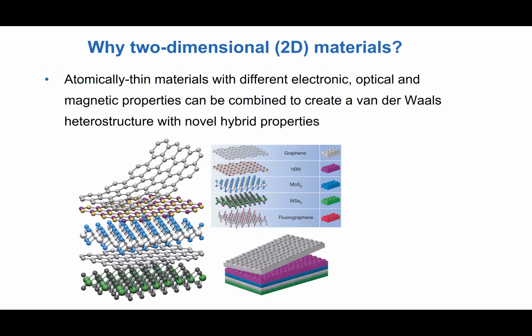In my group, we work primarily with 2D materials, and I think you might have heard about these materials. There are outstanding scientists at Harvard, MIT, and all around the world working with these. The idea is that there is a very large family of materials, more than 5,000 by the last number I know, which have very strong bonds between atoms in the plane and weak van der Waals bonds that connect different layers. These layered or two-dimensional materials have the fantastic property that one can use rather mundane ways like Scotch tape to exfoliate materials down to a single atom thick layer.